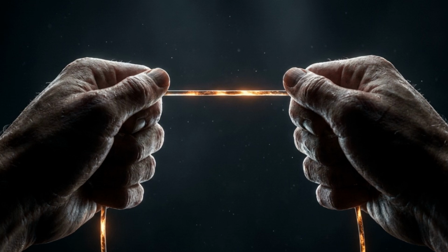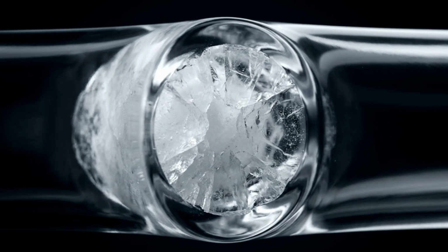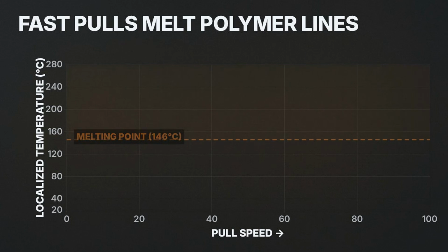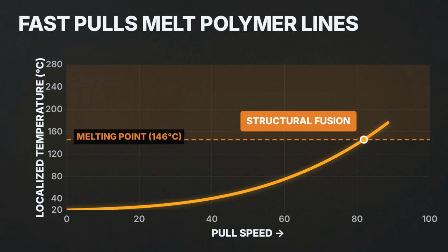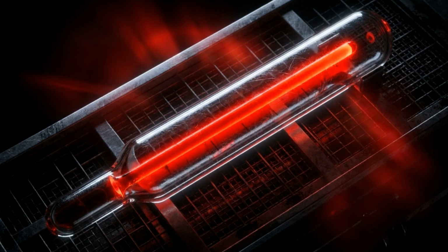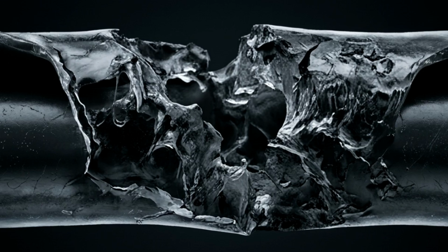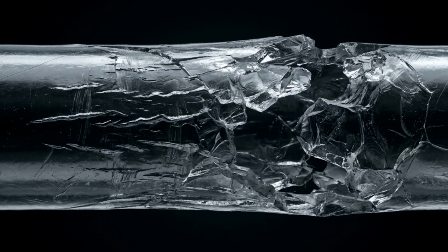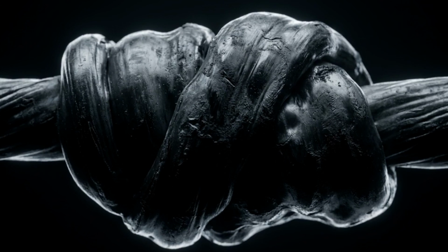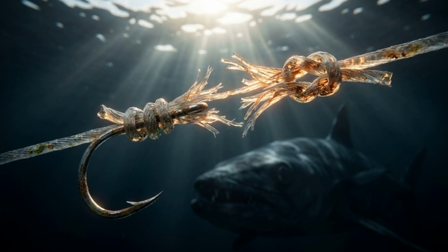By tightening the knot too fast, the angler has effectively created a microscopic thermal bomb that attacks the material from the inside out. In a fast, dry pull, the localized temperature can easily skyrocket past the melting point of the polymer, which for PVDF is as low as 146 degrees Celsius. This causes the stick-slip phenomenon. The superheated, semi-melted surface of the line bites into itself, carving deep microfractures and gouges into the polymer backbone. When this happens, the knot isn't just tight, it's fused and structurally melted, wounded before it ever has to face the weight of a fish.